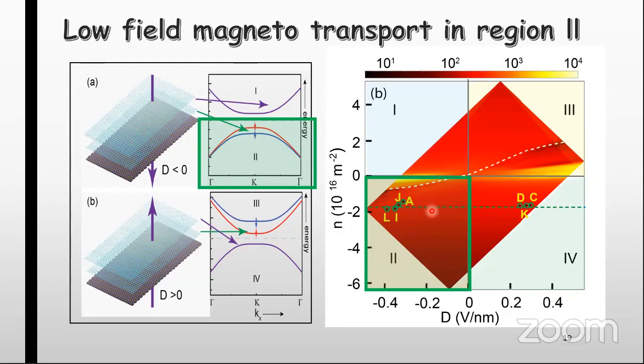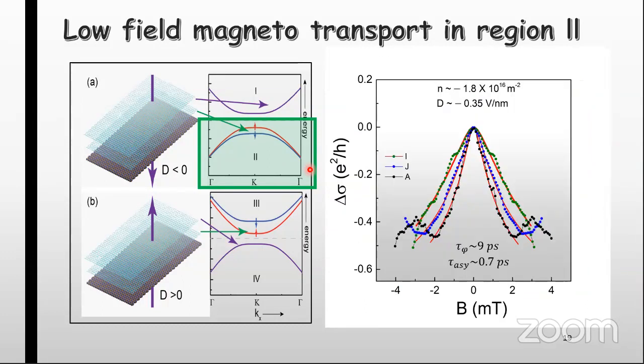Now this is the reason the spin orbit coupling strength should be stronger as per this prediction, and this band should be split. When we did the magnetoconductance measurement here, we found it shows weak anti-localization, and we did the fitting for this curve, shown by this red plot. The relevant time scales we found were a 9 picosecond phase coherence time and a spin-dependent time of 0.7 picosecond. This is the highest spin scattering rate reported till now, which shows there is very strong spin orbit coupling in this system.